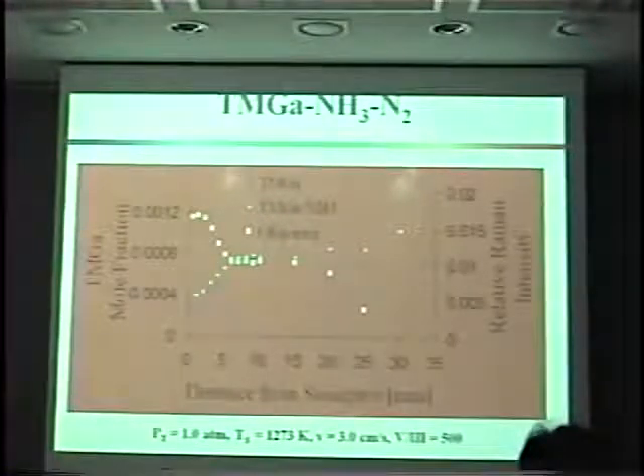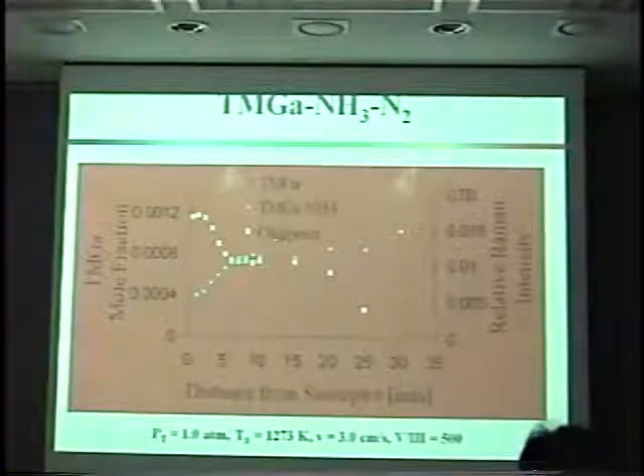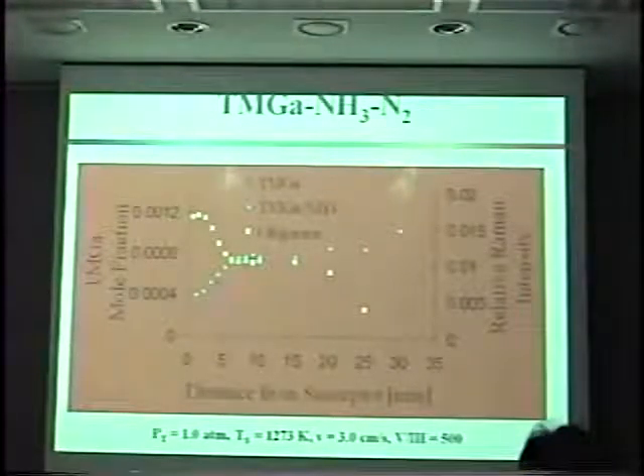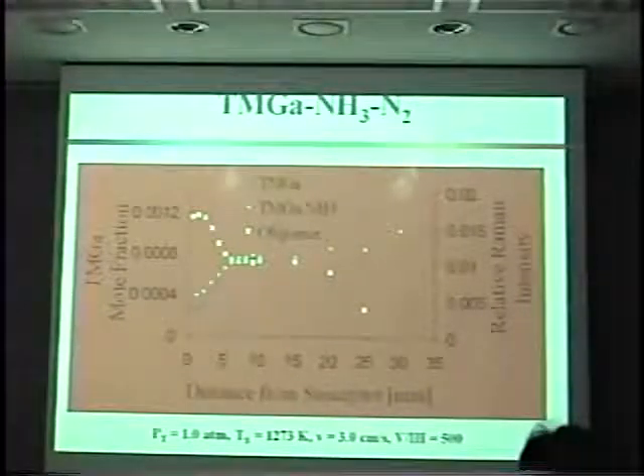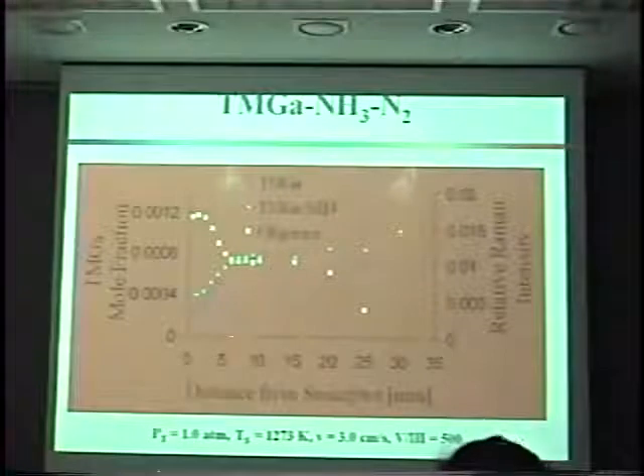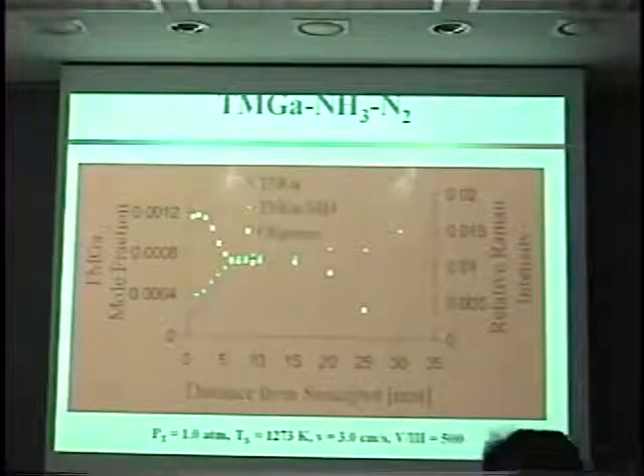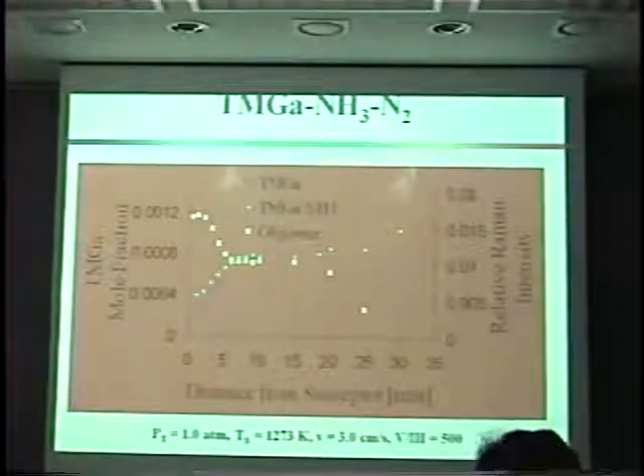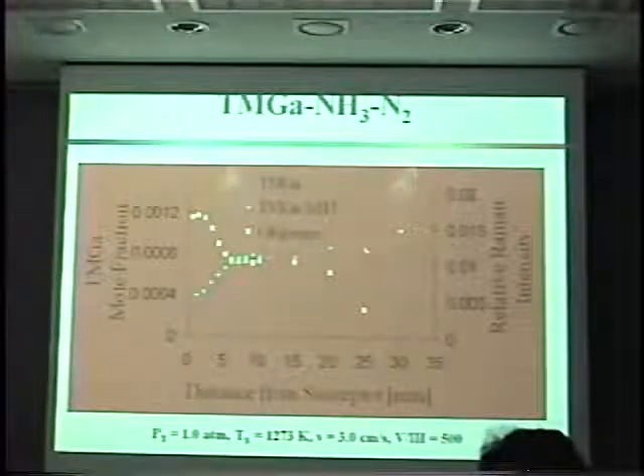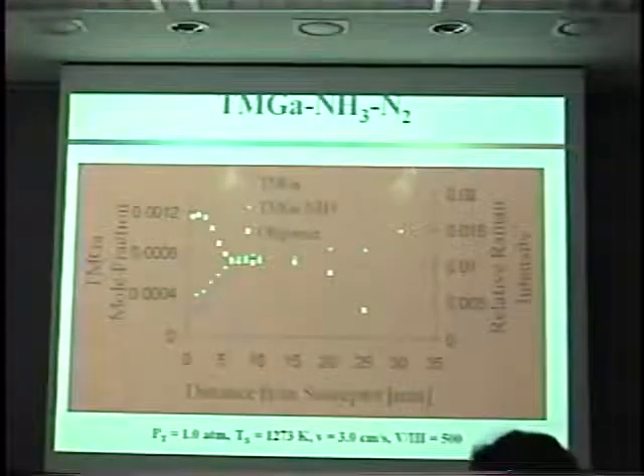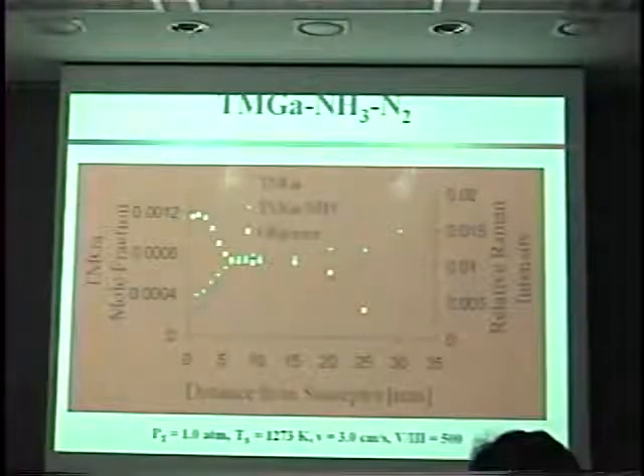This is trimethyl gallium, the adduct and the oligomer again, but with a mixture of trimethyl gallium, ammonia, and nitrogen. That is the real reacting system. So if we look at the trimethyl gallium, we're feeding in trimethyl gallium, but it's starting to disappear, even at low temperature. This is really close to room temperature. And what's happening, of course, is it's starting to form the adduct, and removing that. The trimethyl gallium then will attack the adduct and start to form the oligomer. Even at this very low temperature, you get the oligomer formation.